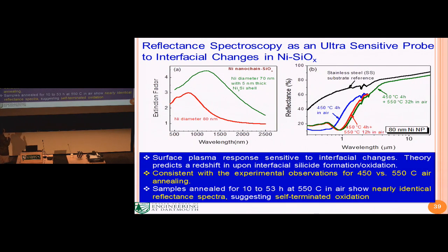Another thing we want to characterize is the optical properties. You find that the optical properties are very sensitive to the surroundings, to the oxidation surrounding the nanoparticle. Here's a simulation showing that if you have a very thin layer of silicide, that will shift the resonance. So we actually performed this kind of experiment. Indeed, we find that 450 versus 550 degrees, we see an obvious shift in the spectrum.